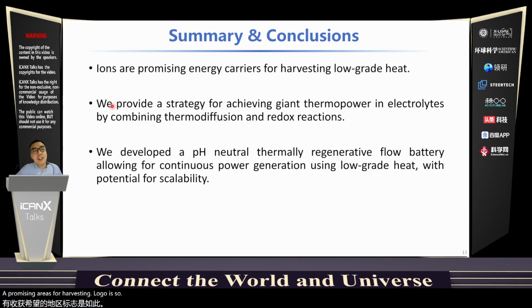So in the first part, we provide a strategy for achieving giant thermal power electrolytes. By combining the thermal diffusion and the redox reactions, we achieve a synergistic effect and a record high thermal power in these electrolytes. We also developed a pH neutral thermally regenerative flow battery in the second part, which allows for continuous power generation using low-grade heat with the potential for scalability.